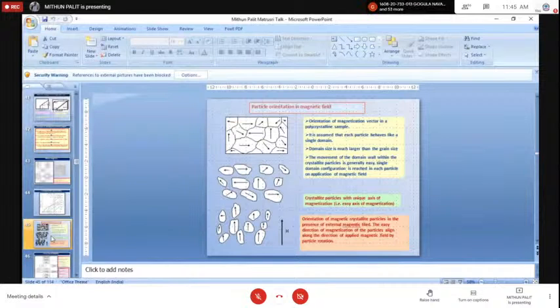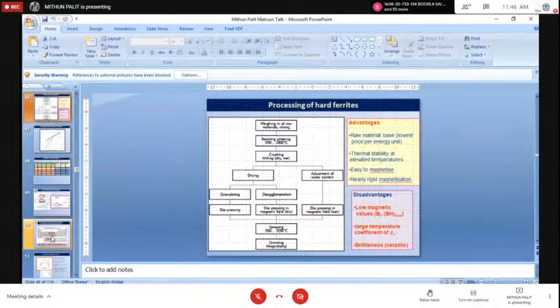Of late, the researchers learned that if we can reduce the particle size and make the particles close to single domain, that means each particle will have only one domain, and in this situation we can orient these particles by application of an external magnetic field, then we are orienting all the particles along their easy direction of magnetization. In this condition, if you compact and sinter and make the magnet, you have a perfect orientation in the magnet. Once this was realized, it was first applied in the case of the ferrite magnet, the hard ferrite. They are basically a class of iron oxides, and there the powders were first made, oriented and then sintered, and the researchers found that this really improves the efficacy of this kind of permanent magnet material.